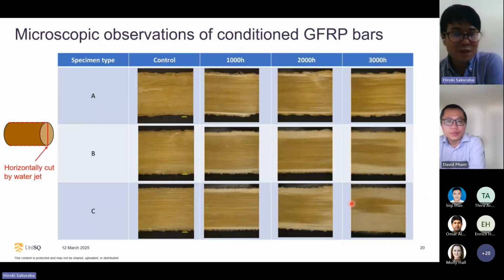This is also another example. We have 3 specimens with different manufacturing parameters. This picture was taken after cutting horizontally by water jet. Control means this is after the interlaminar shear strength test, so we have some horizontal cracks. And after that, we had alkaline conditioning for 1,000 hours, 2,000 hours, and 3,000 hours.